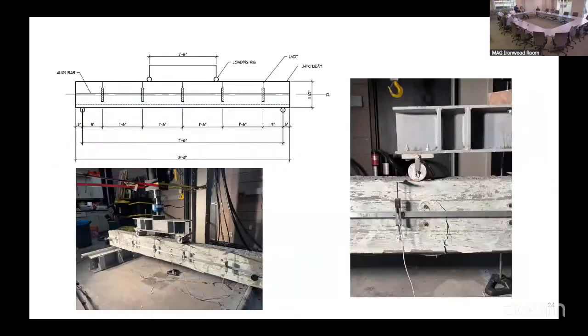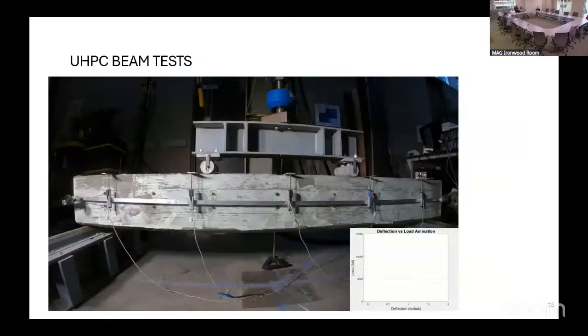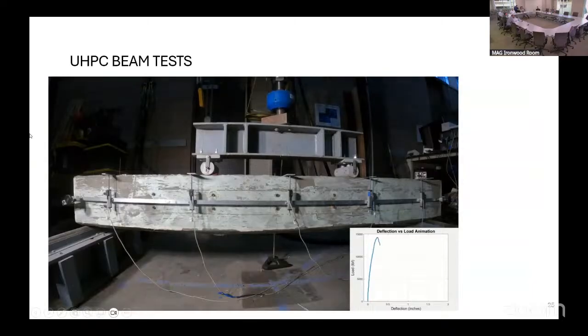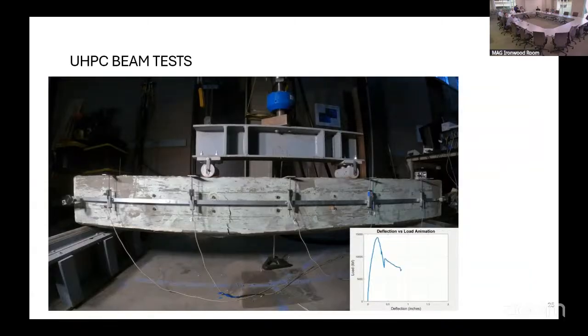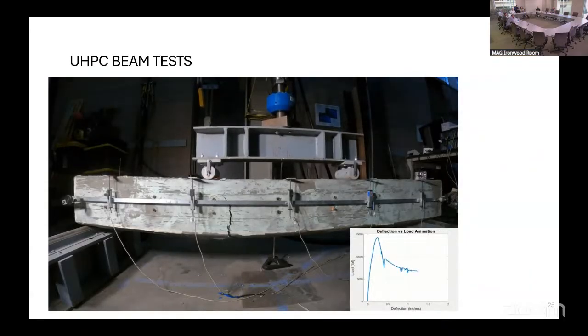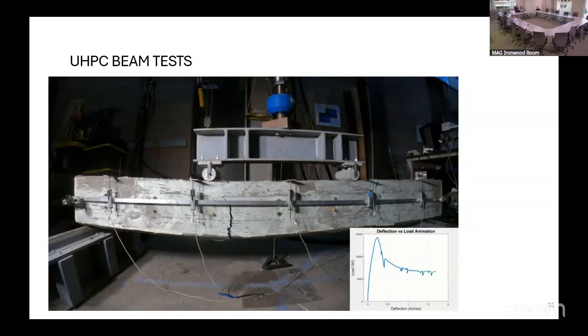Next one. And we've done again the same. Everything we do has to be verified with full-scale samples. So we collect samples and then we test them. Next slide, please. Okay, here's a video again, if you can show. As we apply the load, we measure the load, and it completely fails. And you can see the deflection, almost about 1.5 inch deflection on that 6-inch strip, and after 1.5 inch deflection, it is carrying 8,000 pounds of load. If you look at the load, how it stabilizes.